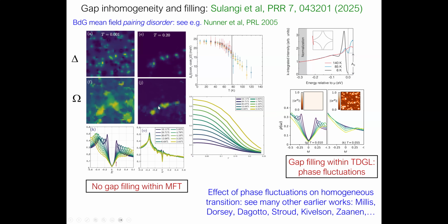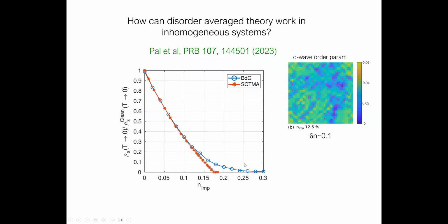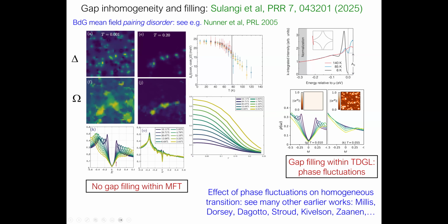So in this sense, we are able to, here's the picture reproduced. Can you guys see my cursor? Yes. Ming, can you see? Yeah, okay, thanks. Yeah, so this is the experimental data reproduced up here. And here's the result of the simulation. The TC is somewhere in the middle here. It's not well defined, so I don't draw a gray line, but it's somewhere around 0.15, 0.17, something like that. And so this looks very similar to what's seen in the ARPES. On the other hand, if you look at the density of states, you don't see gap filling, you see gap closing. So that doesn't work.